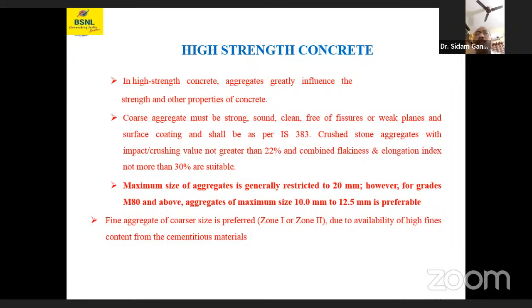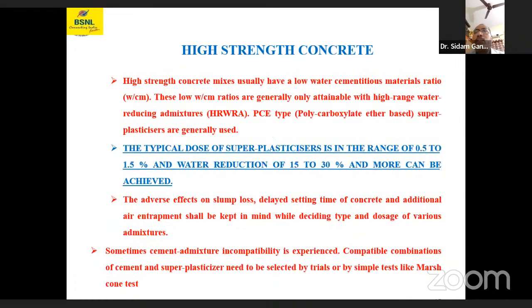Next, the typical dosage of superplasticizer is in the range of 0.5 to 1.5%, and water reduction of 15 to 30% and more can be achieved. The adverse effects of slump loss, delayed setting time of concrete, and additional air entrapped shall be kept in mind while deciding type and dosage of various admixtures. Sometimes cement admixture incompatibility is experienced. Compatible combinations of cement and SP need to be selected by trials or by simple tests like the Marsh cone test.